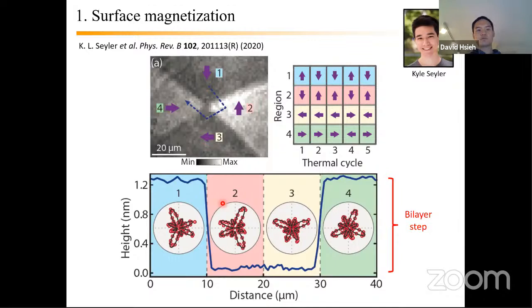And so you can do more sophisticated measurements to really convince yourself that it's coming from the surface. So here Kyle's combined some SHG imaging with atomic force microscopy experiments. Here, for example, are four domains that we've identified via these RA patterns, which direction the big lobe is pointing in. And if you go, for example, from region 1 to 2, that corresponds, it turns out, to a bilayer step in the AFM scan. And every time we encounter a bilayer step, we see that the spin flips by 180. Okay, and so that's consistent with the stacking pattern in strontium iridate, this left, left, right, right. Every time you go down two layers, the spin direction has to flip.